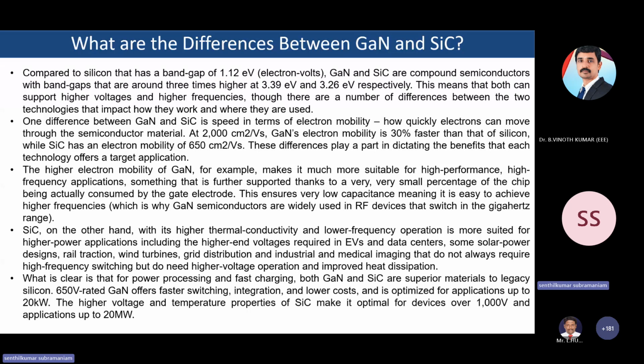So now one can understand the differences between GaN and SiC. Compared to silicon, which has a band gap of 1.12 electron volt, GaN and SiC are compound semiconductors with band gaps that are around 3 times higher, at 3.39 electron volt and 3.26 electron volt respectively. This means that both can support higher voltages and higher frequencies, though there are a number of differences between the two technologies that impact how they work and where they are used.